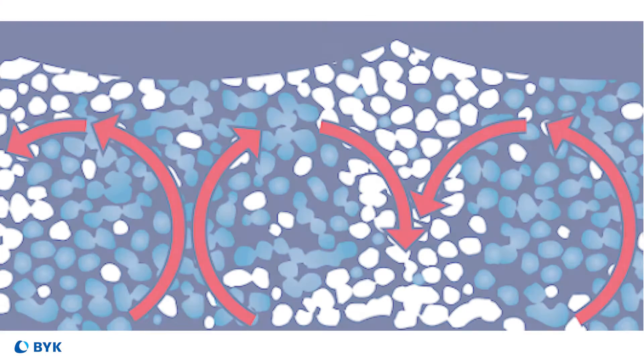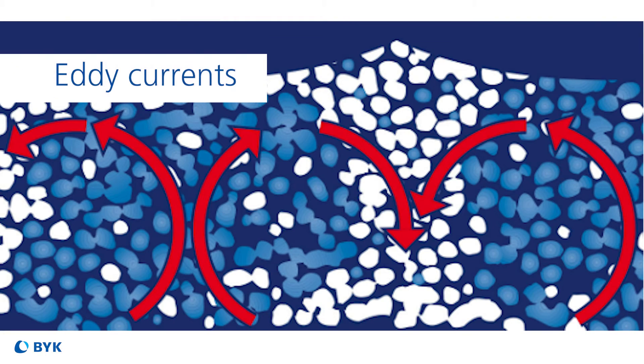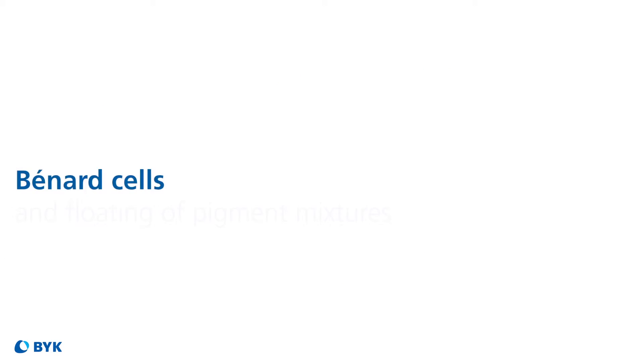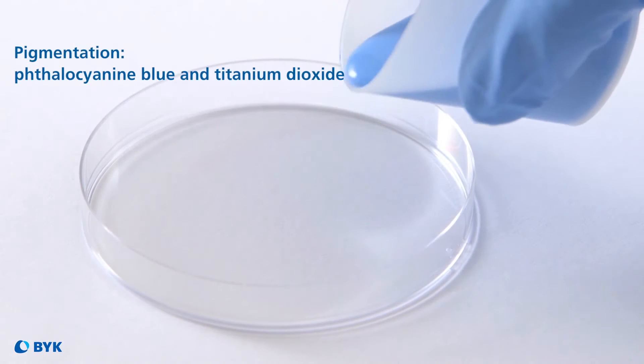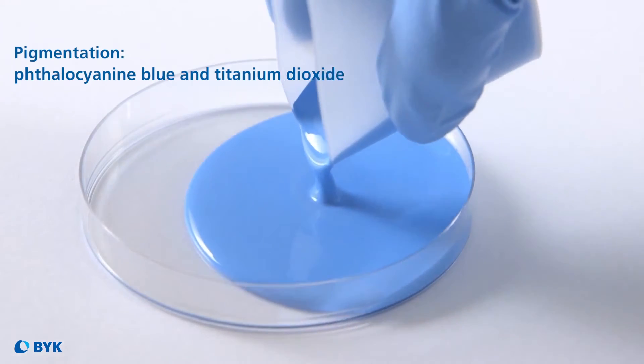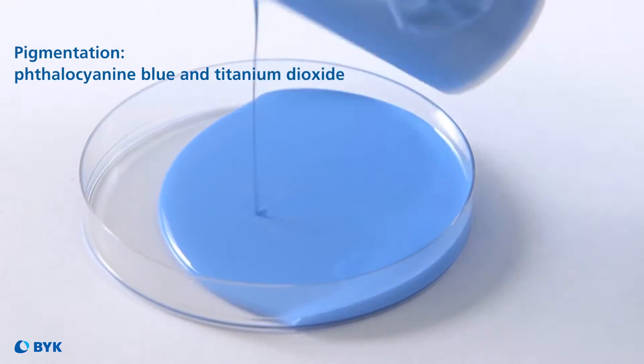For example, as the solvent begins to evaporate, the density increases and the surface tension changes. These disturbances are due to eddy currents creating Bénard cells within the system as it is drying. Pigments will travel with these eddy currents and different pigments have different mobilities within a coating. This can initiate the pigments to shift within the film and no longer be uniformly distributed.